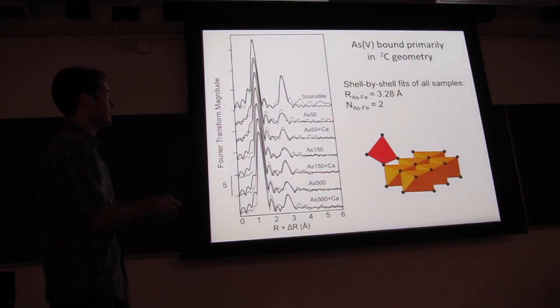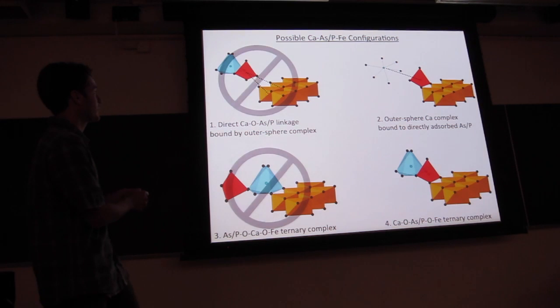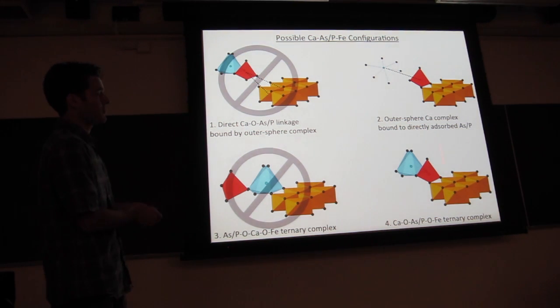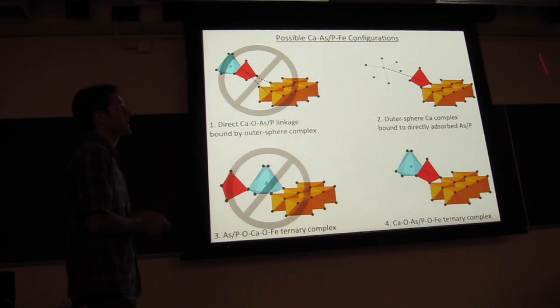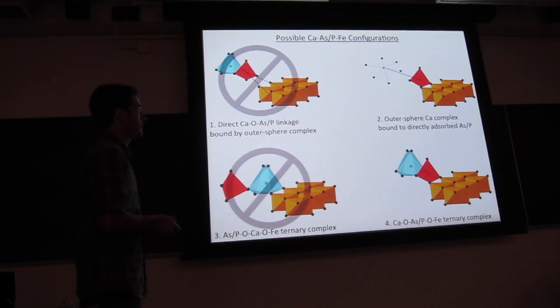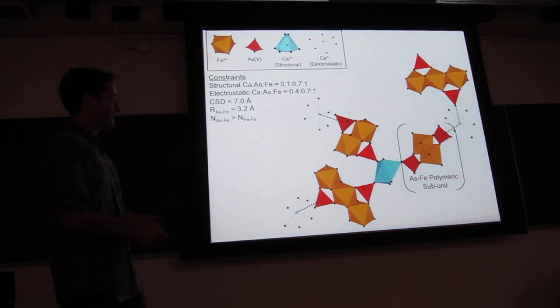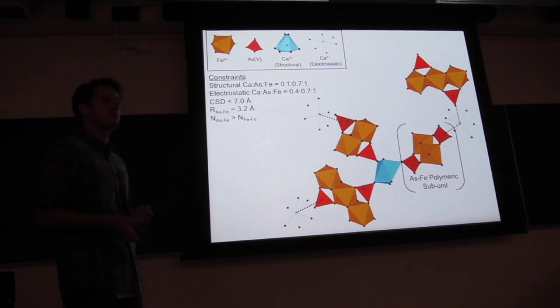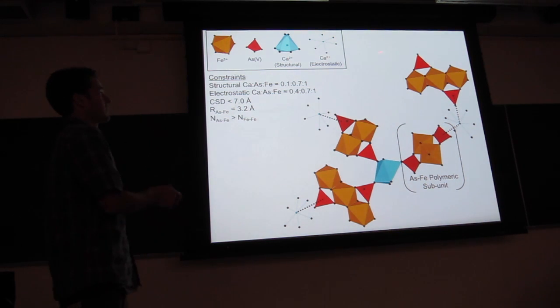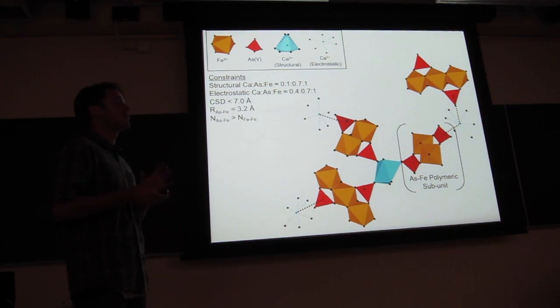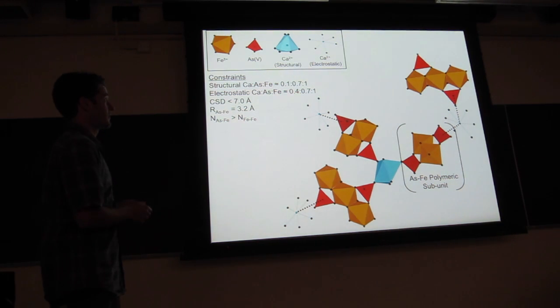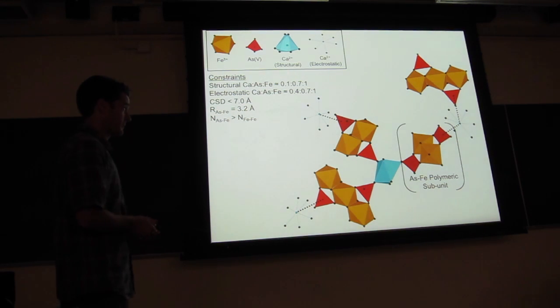So we can then go back to our possible configurations and we can rule these two out. So we're probably going to have this one and this one are both possible based on our data, and we actually expect both of these to occur in our system. So now, taking all of the data that we've got, all of these constraints from the different techniques that we're using, both macroscopic and molecular scale, we can come up with possible structural models of these polymers that form at the onset of electrolysis. And so this sample is going to be derived from data from the AS500 plus calcium sample.